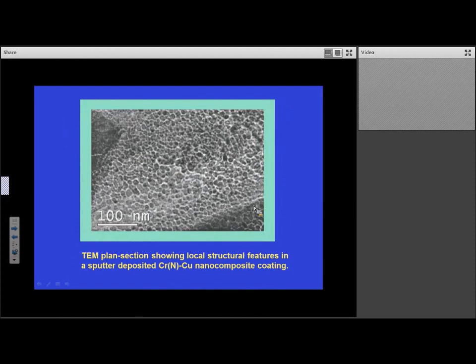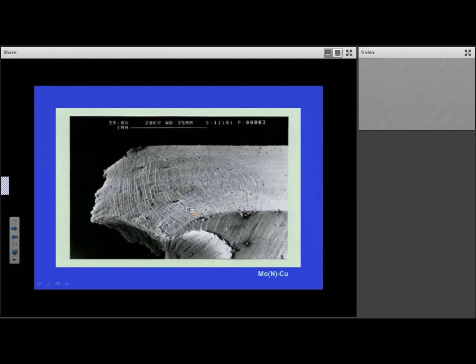And this shows a typical example of such a coating. This is chromium with nitrogen interstitial hardening in a copper grain boundary phase. These coatings are remarkable because they're basically metallic, but they have ceramic-like hardness levels, but metallic-like elastic moduli. And they can accommodate deformation, so they're obviously going to perform very well in a tribological situation because of their ability to absorb and accommodate deformation while still being quite hard.